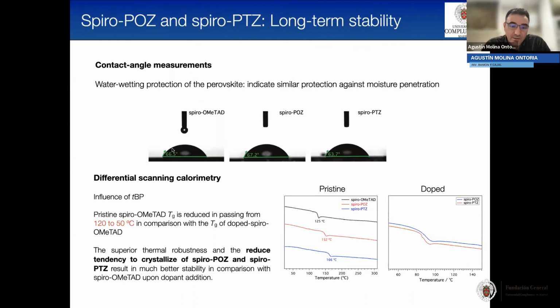The difference is coming from the differential scanning calorimetry. So the pristine Spiro-OMeTAD shows a glass transition of 125 degrees. Our molecules exhibit higher temperatures, 152 and 166. These are pristine hole transporting materials.